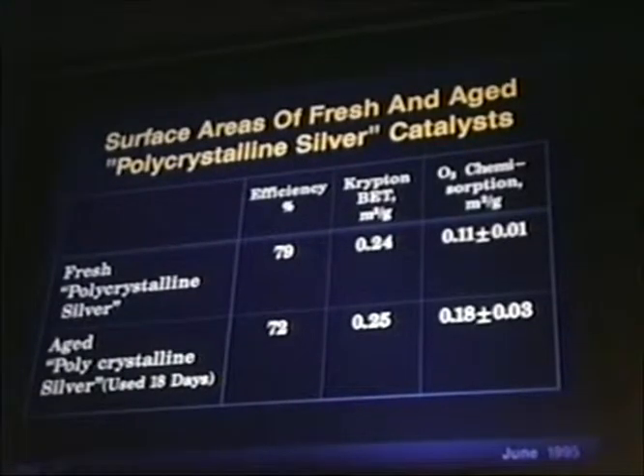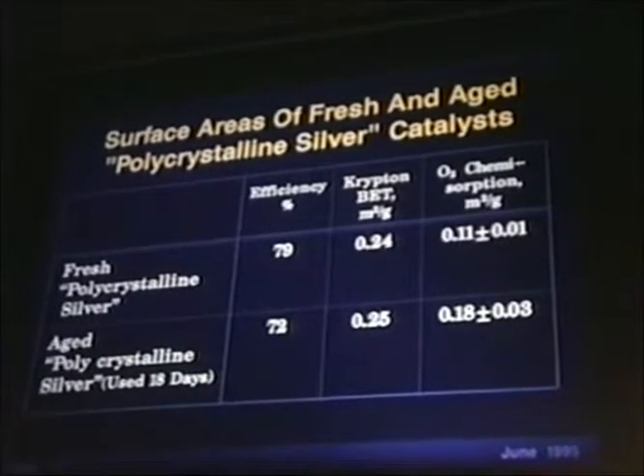The performance was evaluated in the absence of chloride, the necessary gas phase promoter for commercial operation, but to keep things simple, we had done this study in the absence of gas phase chloride promoter. So after 18 days, losing nearly 7% efficiency, down to 72, certainly these observations made us very curious to find out what is going on and what is the cause of this efficiency loss.